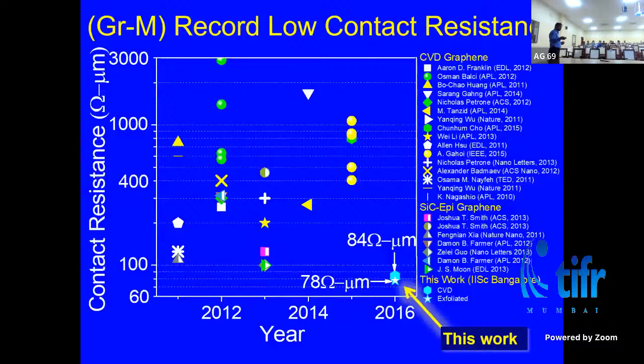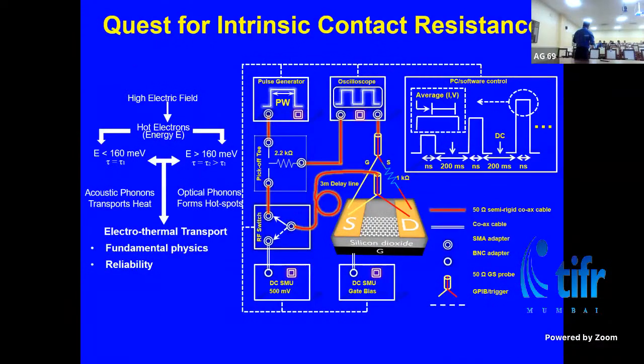Now, anything that we measured so far is all steady state, not fast. Which means we are forcing the current and applying voltage for say a few seconds before you integrate and say that this is the value, right? But when you put the system under stress for that long, naturally you will have a lot of heating at the contact. So you have by default introduced an increased phonon population in the contact area, and that increased phonon population is going to affect your transport properties in the contact area, right? So the numbers that we measured so far are with an elevated phonon population in the contact area.